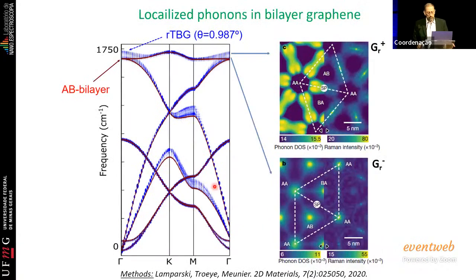Let's go deeper. This is the phonon dispersion of graphene. Okay, so here again, this very point here would be the only Raman active phonon. So you would have the carbon-carbon stretching that you observe in the usual Raman spectrum. But when you rotate graphene, you enlarge the unit cell in real space. You reduce the unit cell in reciprocal space, and this causes what we call zone folding. So you take a lot of phonons from the interior of the Brillouin zone and you fold them at the edge of the Brillouin zone, and a lot of modes are supposed to become Raman active.